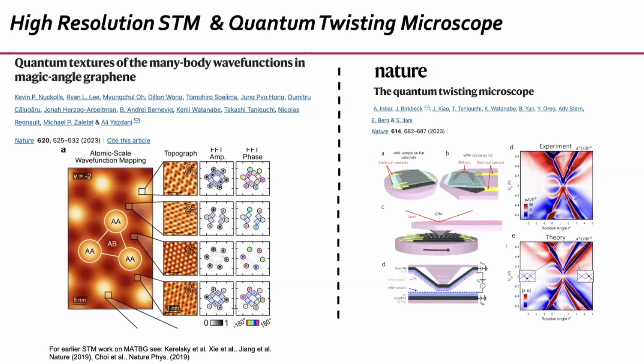And then the group of Shahal Ilani published this new technique, which I think is quite revolutionary, the quantum twisting microscope. For the devices that we and the majority of the community have been making so far, you can choose any angle that you want between the two sheets with very high precision. But once you make the device, that angle is fixed. So what Shahal and collaborators did is they decided to put one graphene sheet on a substrate and the other graphene sheet on the tip of an atomic force microscope, and they could bring one on top of the other. The nice thing is that they can rotate this atomic force microscope tip in situ. So now you have in situ electronic control of your twist angle. And that was tremendous.